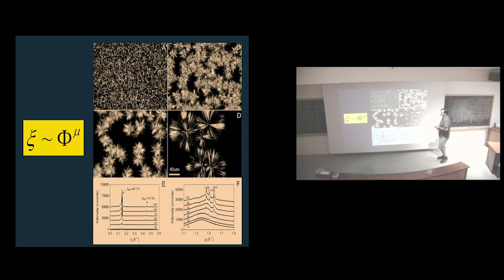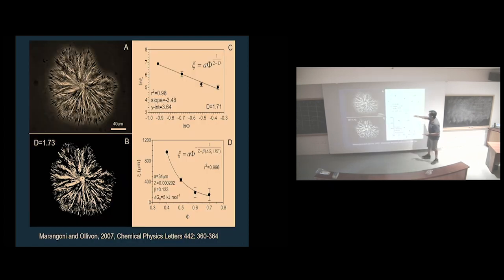We did a whole bunch of experiments, looking at how the size of the cluster scales with the volume fraction and the power law, and these are the kind of systems. This is very bizarre because these are spherulites. So we were considering that these are actually clusters of crystals, and even under these circumstances, we actually get scaling behavior characteristic of a fractal object. And we were getting, again, fractal dimensions that people don't scream at you when you put 1.7.